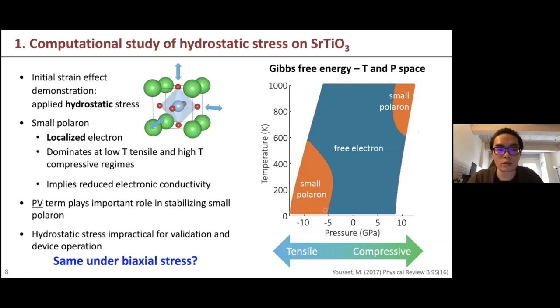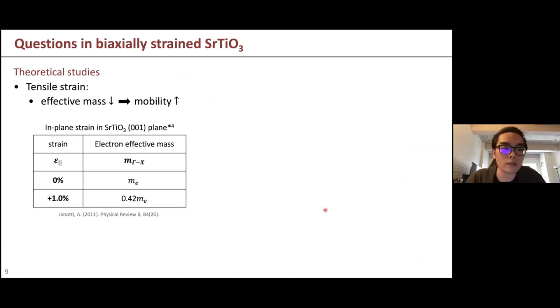So the next question is, do these observations still hold under biaxial stress? There is a previous theoretical study about how biaxial strain affects the electron properties. It predicts that the effective mass of the electron will decrease when you apply a tensile strain biaxially, not hydrostatically. If you apply a 1% biaxial strain, you can decrease the electron effective mass to 40%. So they predict the mobility of the electron will go higher, and in the end you will have a higher conductivity.